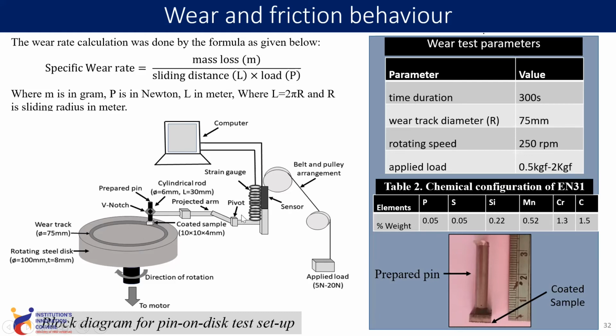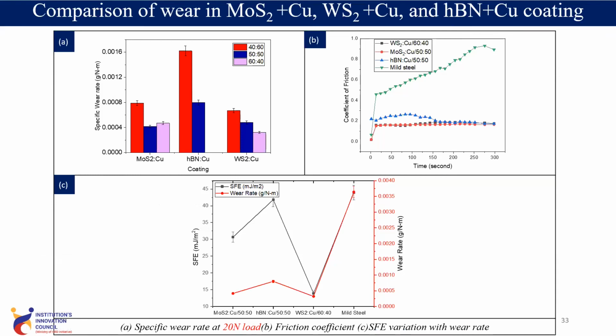By capturing the data on the computer, we have obtained the coefficient of friction and wear in different coatings, in which we can observe that all the samples showed a low specific wear rate and low coefficient of friction as compared to mild steel. This is the coefficient of friction for the mild steel surface, and all other samples showed low coefficient of friction as compared to the mild steel surface. We have also shown that these all have a low amount of surface free energy, so they are showing good tribological property.